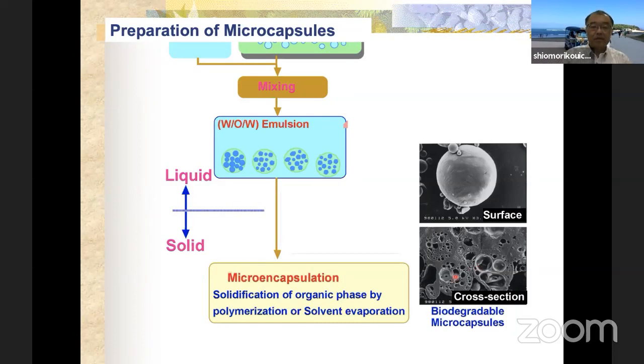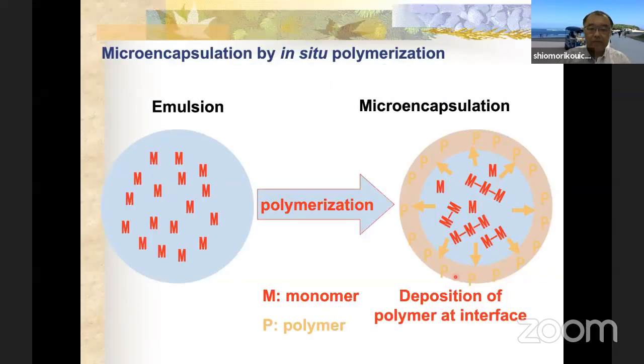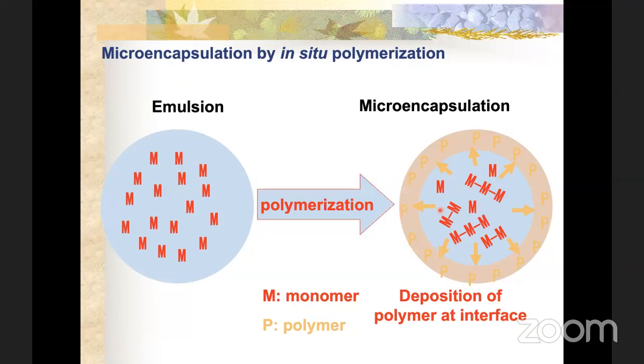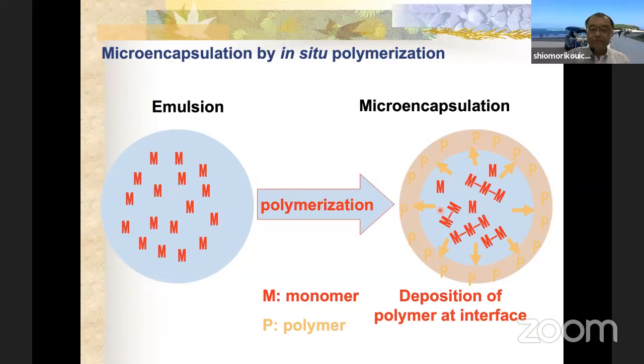Okay, so let me move to the preparation mechanism. The initial polymerization mechanism: the organic phase contains monomer materials and a polymer compound. The reaction is started by radical polymerization. So monomer polymerizes to dimer and polymer. The formed polymer was deposited at the interface between the organic phase and the aqueous phase like this, to make a wall of the particle.